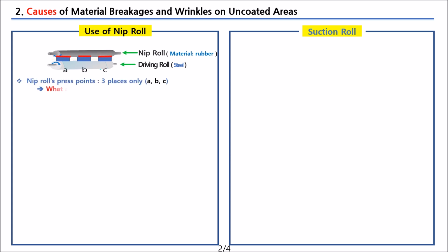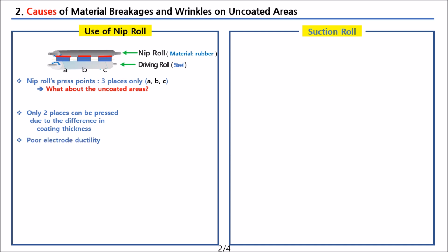When we look at the causes of material breakages and wrinkles on the uncoated areas, regarding the nip rolls that are currently used, in the case of the coating pattern as shown in the figure, the nip roll touches the electrode at the three places of A, B, and C, which are the coated areas, and there are no touches in the uncoated areas. The nip roll touches the three places on coated areas due to the difference in the thickness of the coating. However, the pressure actually applies only in two places, and the material breakages and wrinkles occur due to the cause of poor electrode ductility.